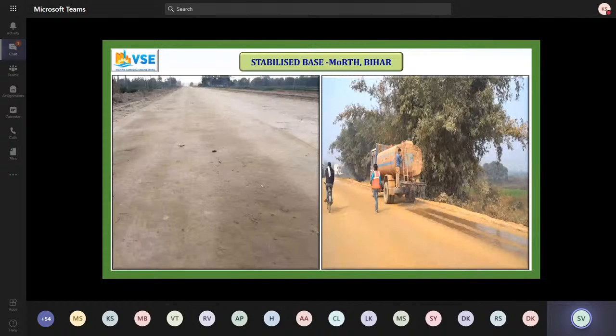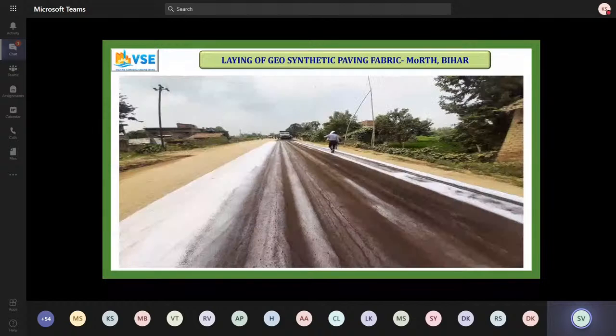And then here we used a geosynthetic as a SAMI layer. Basically, since we're using cement, they're bound to have certain superficial cracks on top. So this is to arrest the cracks coming into the BT layer. We have gone for the SAMI synthetic paving fabric. So on top of that, we spread the BT. So here we haven't used DBM because the traffic is less than 20 MSA.